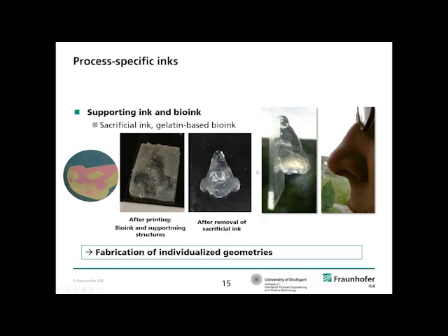We can, with these additive techniques, of course, form individualized morphologies, anatomies. This is only an example. Nobody needs a hydrogel nose, of course, but it is a quite complex structure, and you can see here, for printing a structure with such cavities, you need a special or an additional supporting ink that will then, after the printing process, be removed. And this is an additional challenge to have these kinds of materials that can be combined with the bio ink and then be removed after printing.